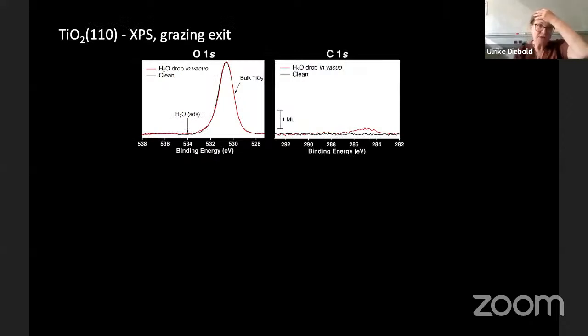And if you look in with X-ray photoelectron spectroscopy with grazing exit, this is the oxygen 1s, this is the clean surface, and this is after we have exposed it to liquid water in this little side chamber. You can see a little bit of a shoulder. This is because we have a little trace of OH groups forming on the surface, but really very little. And there's a little bit of hydrocarbons, but very, very little.